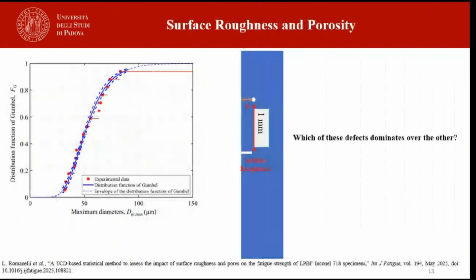Porosity is another common defect in additive manufacturing parts that has a significant impact on fatigue behavior. Here, we aim to investigate, in the presence of both defects, surface roughness and porosity, which one of these defects dominates over the other. Experimental results show that the maximum diameter of spherical pores is almost 85 micrometers. So we choose the maximum diameter for porosity and surface roughness, and a distance of 1 millimeter is selected between them to avoid any influence on each other.